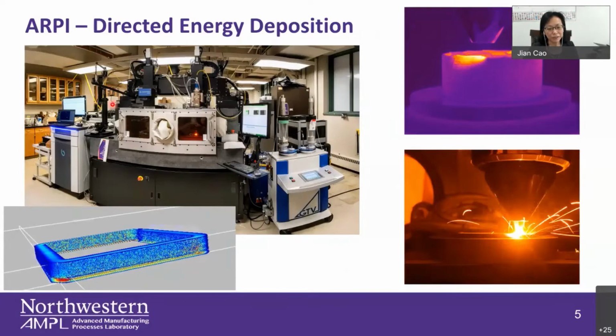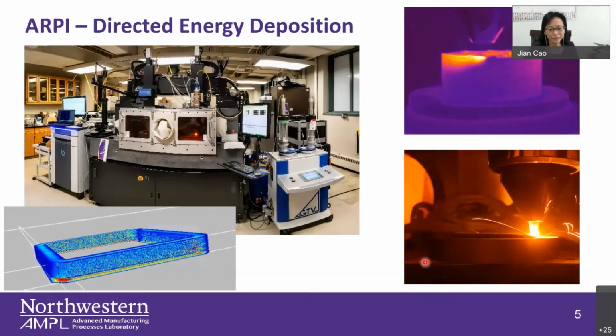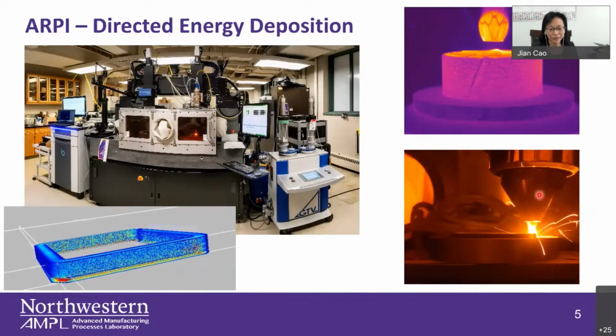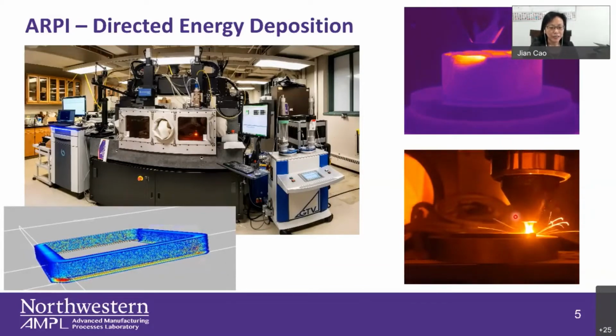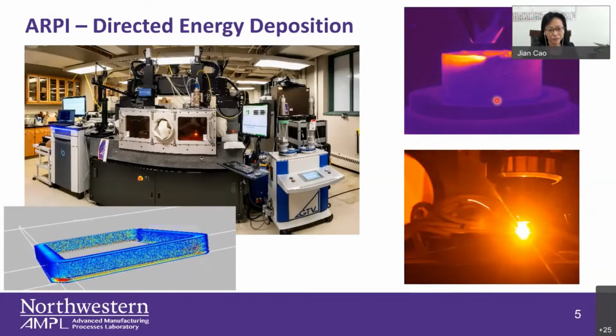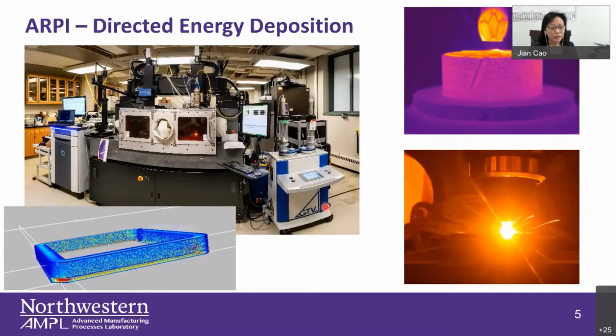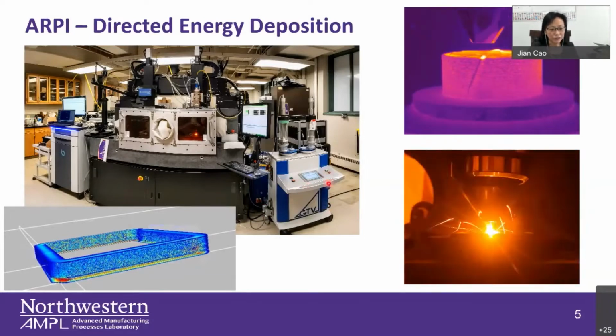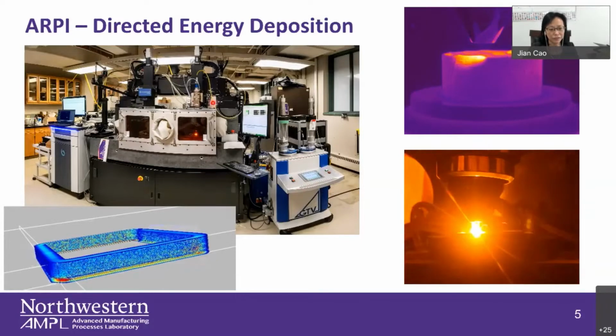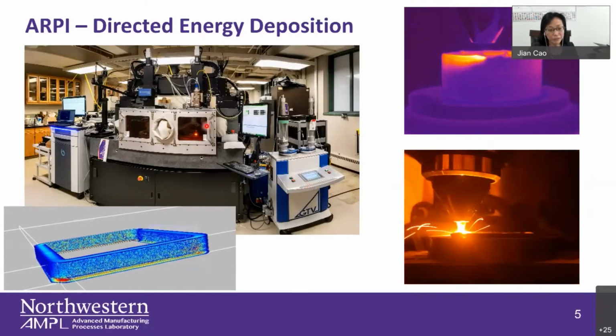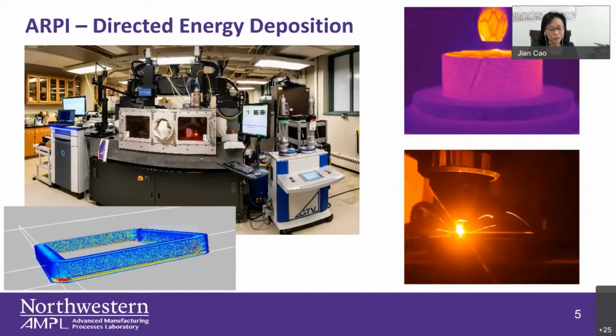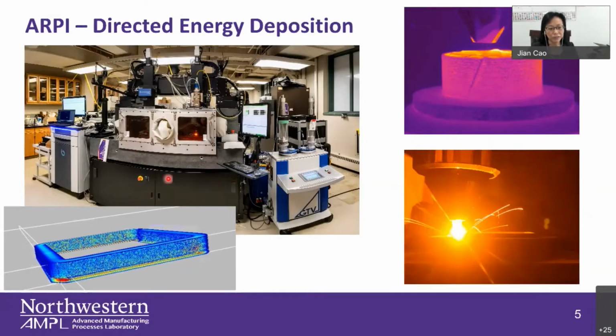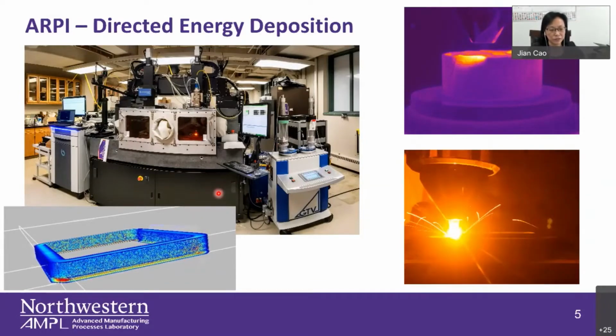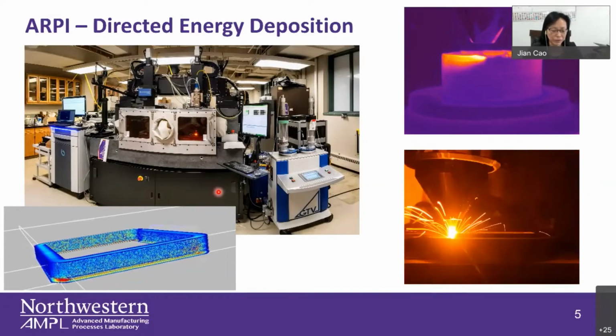We call it ARPI. Basically you have the laser power, and then you have the coaxial nozzles, powder depositions coming in, and then you monitor it with the infrared camera, as well as you have different hoppers, and then we can control the powder flow rate, and also the environmental chamber, so we can also process materials that are probably a little bit more reactive, right?